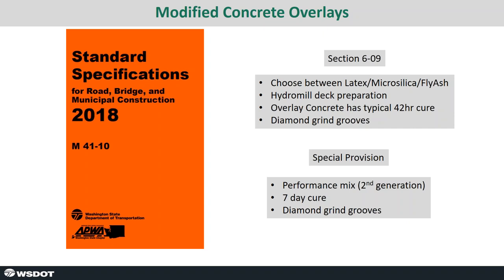And so a typical job, we will do a hydromill deck preparation, which means we will take about half inch to 1 inch of good concrete off and remove all the bad concrete. Typical overlay cure is about 42 hours. And then we are specifying diamond grinding longitudinally again for the deck overlay, similar to what's done on new bridges.